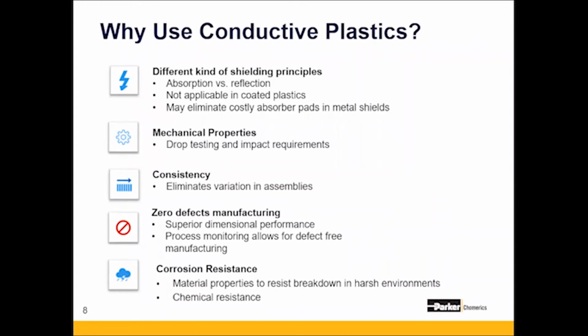The other thing is you can eliminate things when you mold a plastic part. I had a customer once that had a 2-part clamshell design. It was a non-conductive plastic. They were coating it with a conductive copper paint, and they were getting a lot of resonance and bounce back from the signals inside. So they got some pellet samples, molded a conductive plastic part, and because of the absorption properties, they reduced the steps in their design. They eliminated the masking, they eliminated secondary absorber pads.